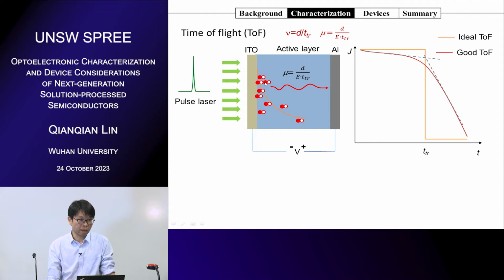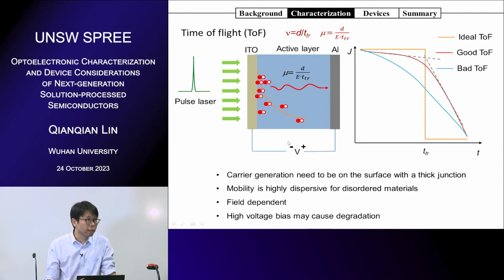This is the first thing. And the second, some carriers may go directly to the counter electrode, but some carriers could be scattered by the nucleus, by the grain boundaries, and they may not go very straight, and the distance could be extended. That's why we get another reason for the dispersive curve. But anyway, this is also a good TOF, but for some materials we do have very bad TOF, and then we do not see any kink from the curve or the decay. So we cannot get a very valid or reliable transient time from the TOF measurement. That's the drawback of this measurement.